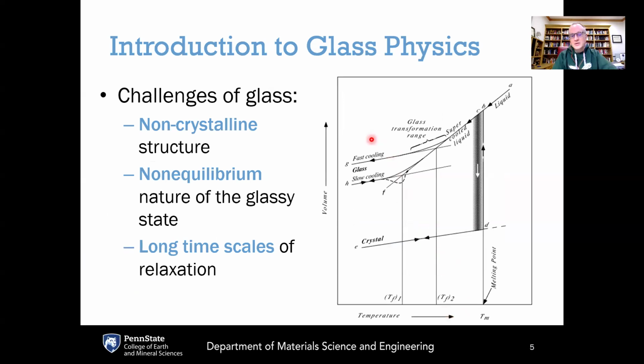And this points back to some of the inherent features of what makes a glass a glass. We can see that on this volume temperature diagram on the right. What happens to make a glass is that you start off in the liquid state here in the upper right. The liquid state is at high temperatures and high volume. As a liquid cools, if it stays in equilibrium, what happens is that when the liquid cools just below its own melting temperature, it should undergo crystallization. So it should rearrange the atoms in the liquid from their disordered liquid structure into an ordered crystalline configuration.